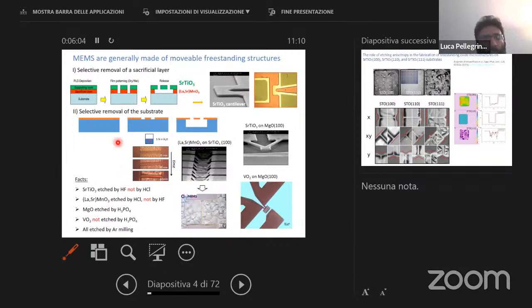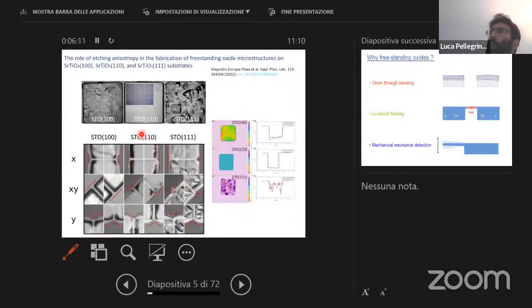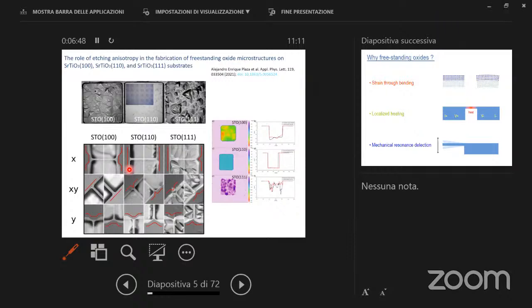So this is the main recipe that we use to fabricate the structures, and then I will move to show another example, that even choosing the right crystallographic orientation of the same substrate, which is STO, we can have different fabrication conditions. For example, we can have rough surfaces after etching or smooth surfaces after etching, and we can tune the geometry of the clamped regions by choosing the proper orientation. I will not go into detail of this recent paper, please refer here for further information.